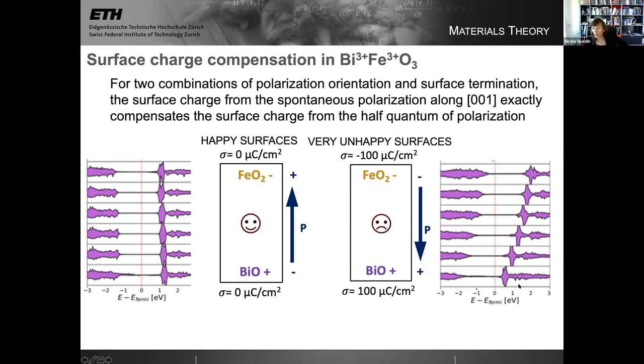This is what a ferroelectric usually looks like, a thin film of a ferroelectric. You see there's a strong internal electric field which causes the bands to bend. You can also see that the top of the valence band starts to overlap the Fermi energy at the top, and the bottom of the conduction band at the bottom. This is making holes up here to try to compensate the negative charge and making electrons down here to try to compensate the positive charge. So this is a typical ferroelectric slab with the net polarization. In the happy configuration, there's no internal electric field because there's no surface charge.